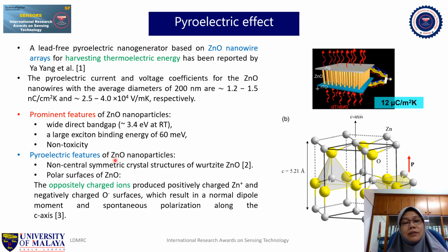Furthermore, zinc oxide nanoparticles also have pyroelectric features. The structure of zinc oxide is wurtzite, so it is under the category of non-centrosymmetric structures. It has polar surfaces, whereby the wurtzite zinc oxide, as shown in this figure here, has attracted opposite charge ions on its surfaces. So with that, there will be a normal dipole moment along the C-axis of the zinc oxide structure.